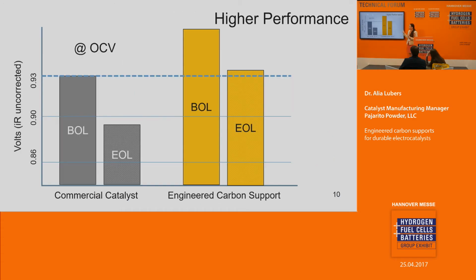So just looking at OCV, comparing a conventional catalyst to our catalyst, beginning of life is before the accelerated stress test, and end of life is after the stress test. And this is using our carbon with an in-house platinization on the cathode side of a PEM fuel cell. So what we can see, just in OCV, we are able to have a higher OCV after our accelerated stress test. It is higher than the beginning of life of the conventional catalyst. And of course, the beginning of life is better than the OCV for both commercial catalyst tests.